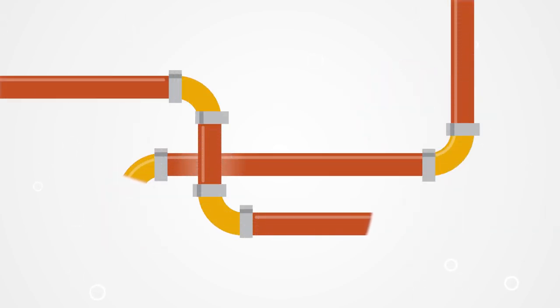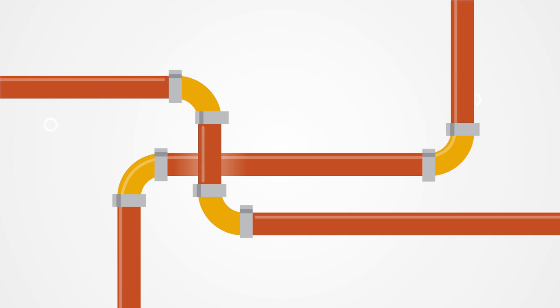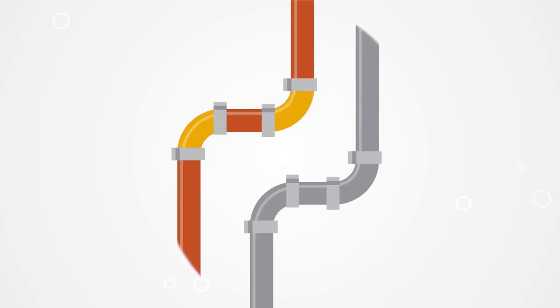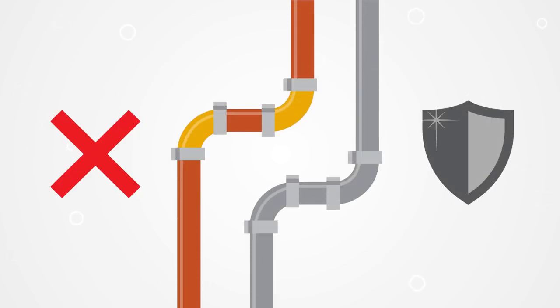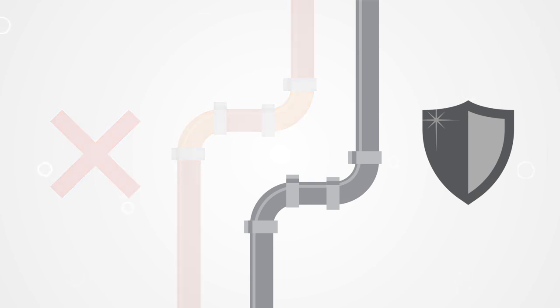Now that many plumbing systems are moving to plastic PEX piping, the corrosion has only one place to go, the brass fittings, which make up a small percentage of the surface area of the plumbing system. With systems totally made up of copper pipe and copper and brass fittings, the corrosion is evenly spread on a much larger surface area throughout the system. This is the reason the conversation around corrosion resistance is so important when talking about PEX fittings. Stainless steel's superior corrosion resistance will outperform brass, especially due to the very thin wall structure of metal PEX crimp fittings.